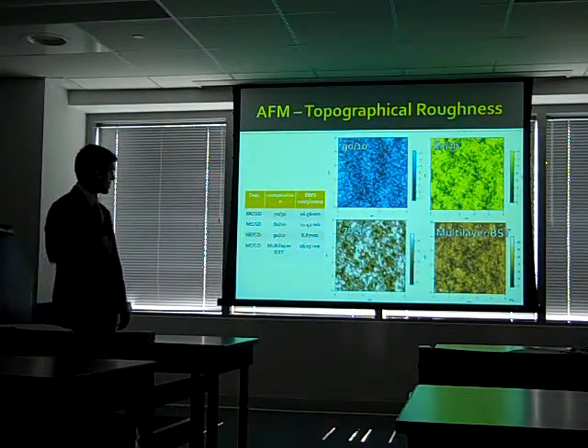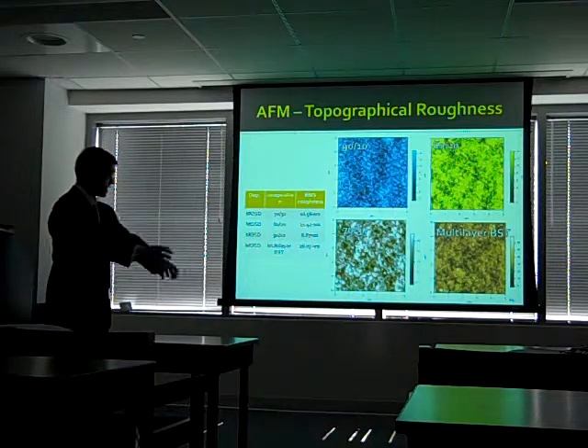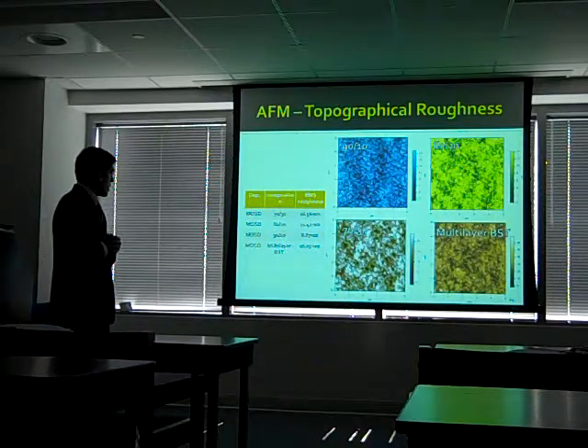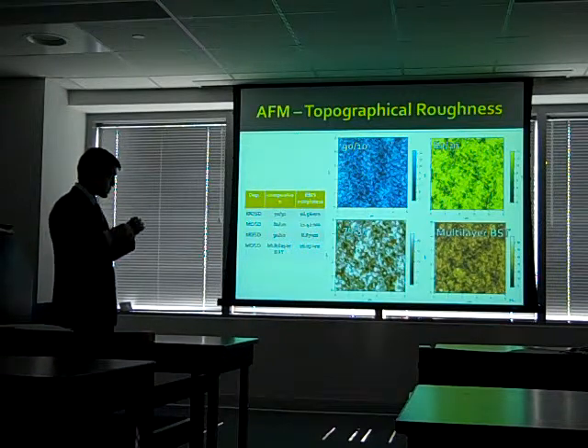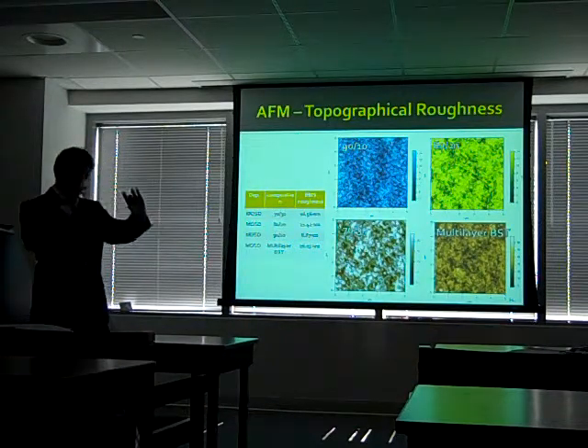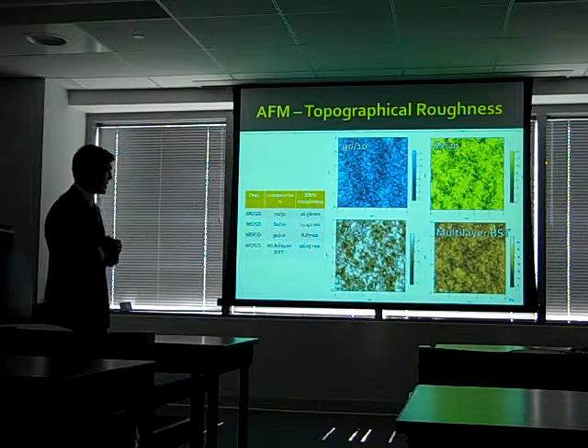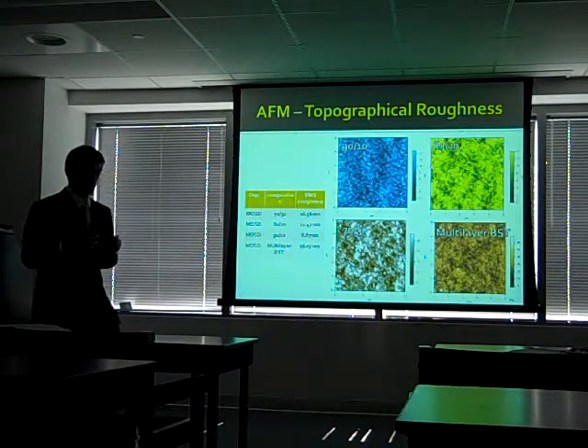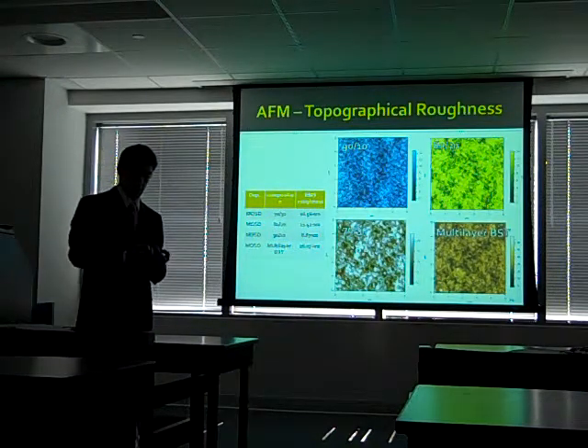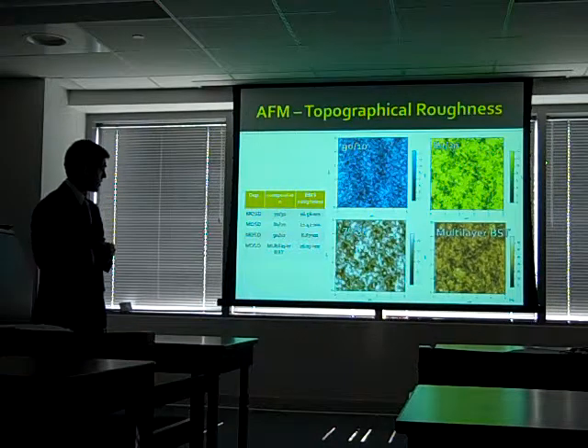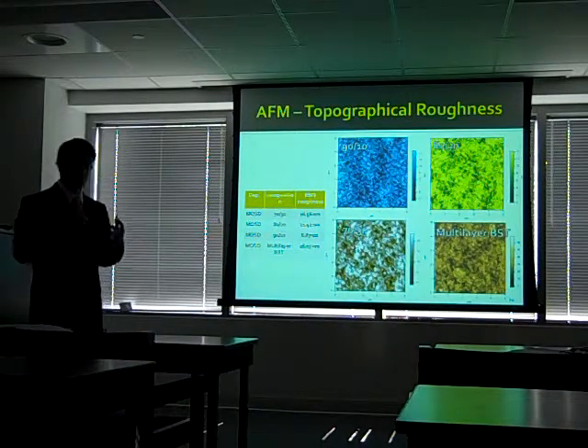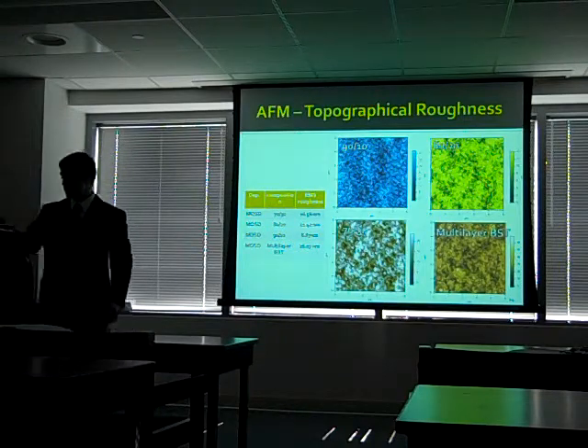Atomic force microscopy was also used to understand the topographical roughness. But the results of modeling seem to indicate that the inclusion of a roughness layer in the model wasn't necessary. There were some cases where the mean squared error wouldn't reduce sufficiently, and in those cases, adding a roughness layer helped, and that would indicate that the film was particularly rough.